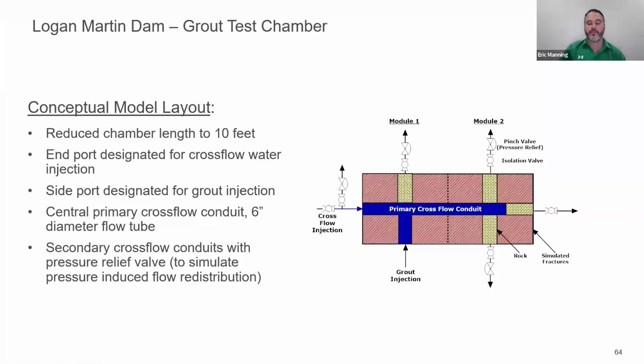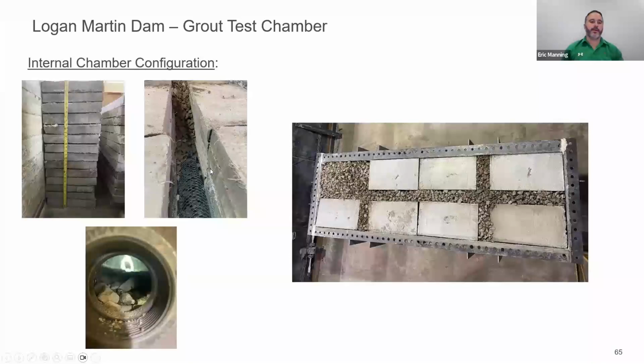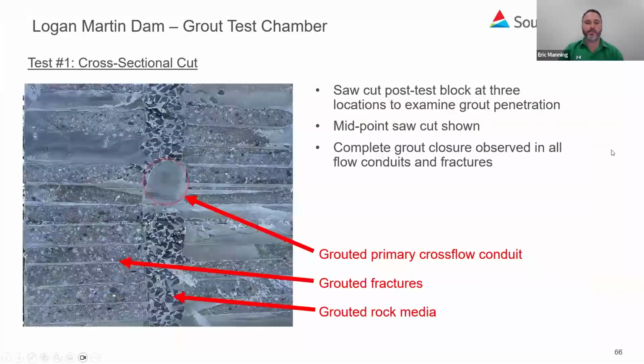Just a few years ago, we converted this test from what originated as a static test, where we had a test chamber filled with geomaterial to simulate karst, to now where we modified the box, reduced its size, and the setup now simulates a karstic tube that runs down the length of the test chamber. We introduce unrestricted flow that goes from one end to the other, then grout through the side, intercepting the cross flow to determine which mixes are more effective at grouting off this cross flow condition that we sometimes encounter out at Logan Martin.